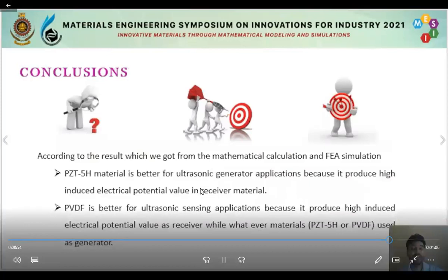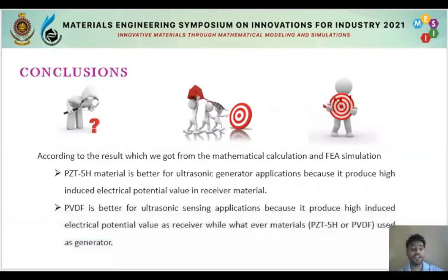And finally, the conclusion was derived according to the results which we got from the mathematical calculations and finite element simulation results. The PZT5H material is better for ultrasonic generator applications because it produces a high induced electrical potential value in the receiver material. And also PVDF is better for ultrasonic sensing applications because it produces a high induced electrical potential value as a receiver, whatever the material used as a generator.